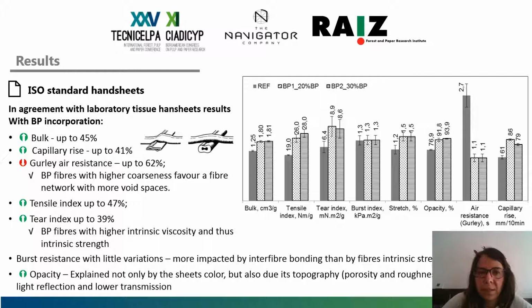To further complete this work, we prepared also typical ISO standard handsheets, and we found that the analysis of these sheets revealed similar trends to the results we found on the laboratory tissue handsheets. So the incorporation of bark resulted again in an increase of bulk and capillary rise. And in case of Gurley air resistance, lower values, which are attributed to the fact that we are incorporating once more fibers with higher coarseness that favor the formation of a network with more void spaces.